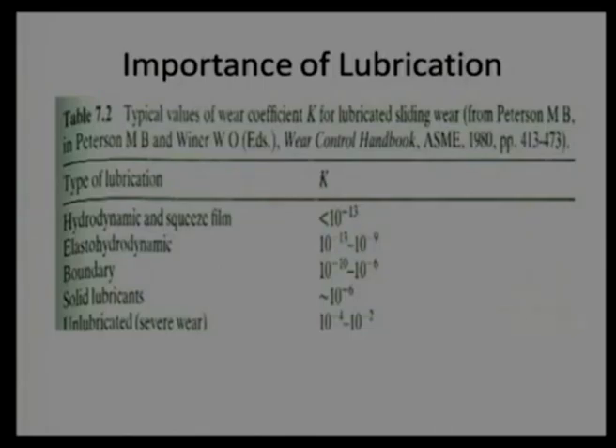So, when we compare wear rate between unlubricated case and solid lubricated case, what we get? Almost a difference of 100. If I say wear rate is 100 units for unlubricated case, we may reduce this wear with the solid lubricant to 1% of that, a huge difference. Obviously, the component life can be increased by 100 times, by properly choosing solid lubricant.